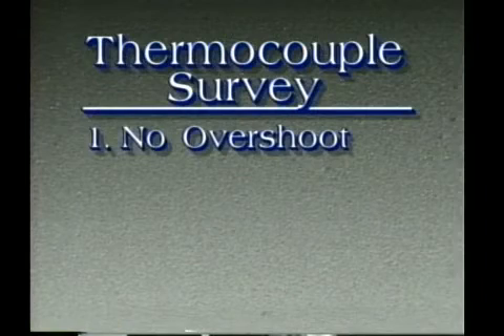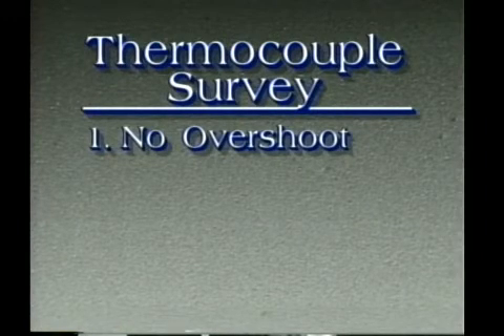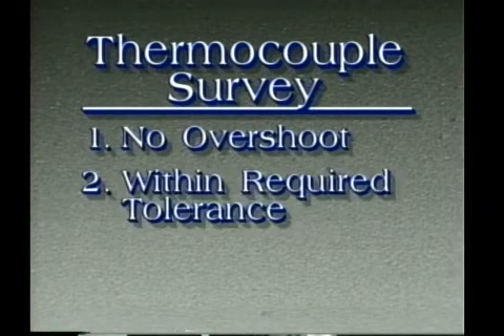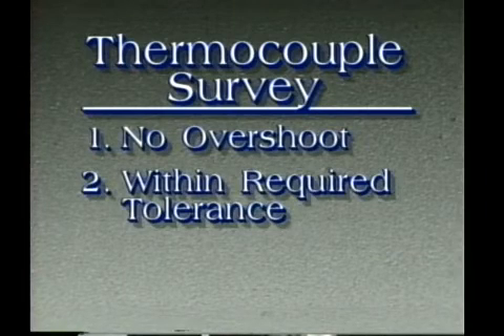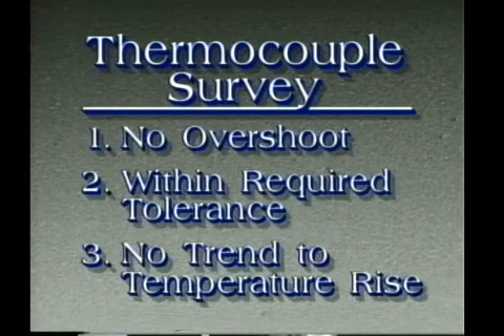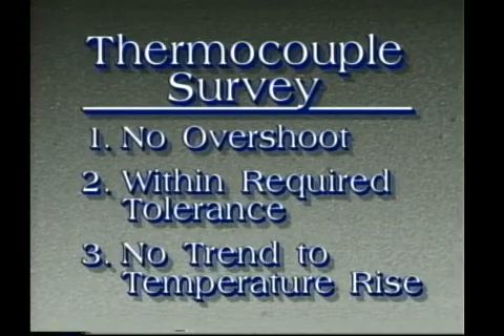When checking thermocouple surveys, 3 critical items must be examined. 1, that no overshoot occurs as the temperature approaches the required temperature range. 2, that all reading thermocouples are within the required temperature tolerance. And 3, that there is no trend toward a temperature rising for longer soak periods after the initial 30-minute survey is finished.